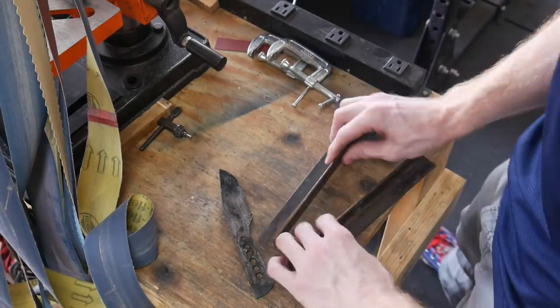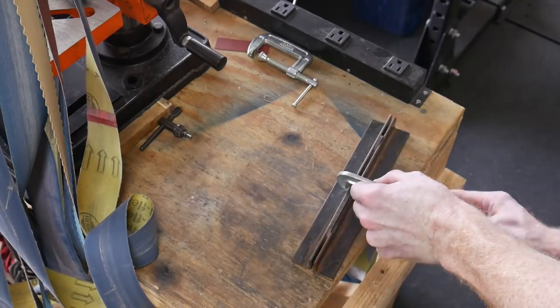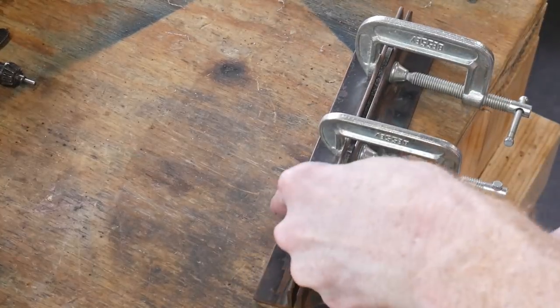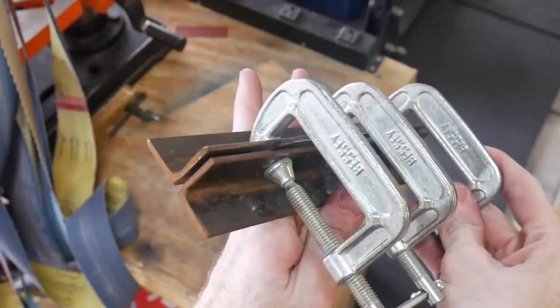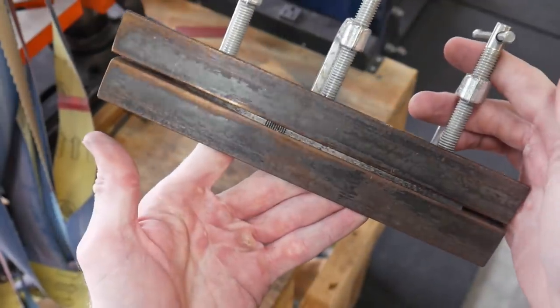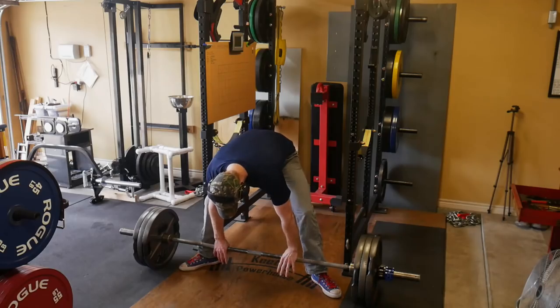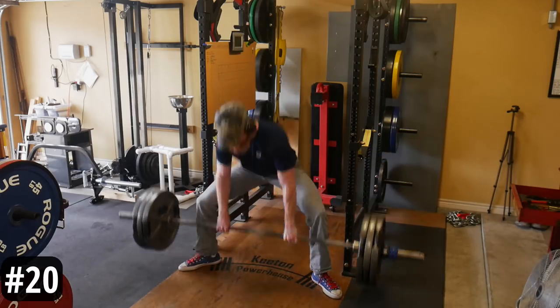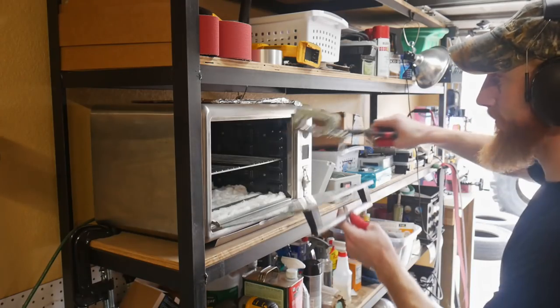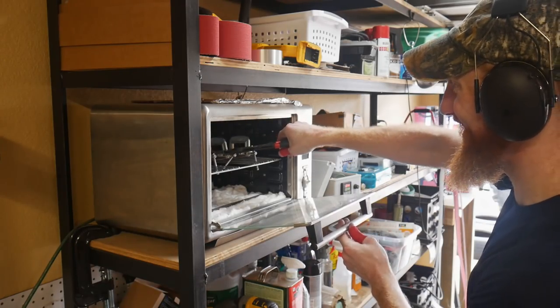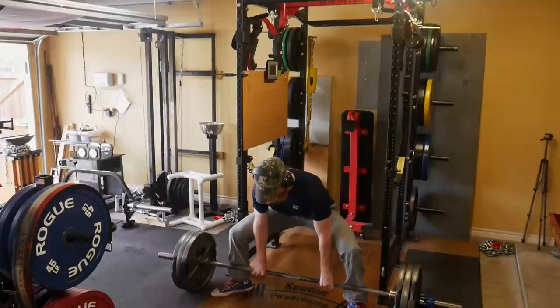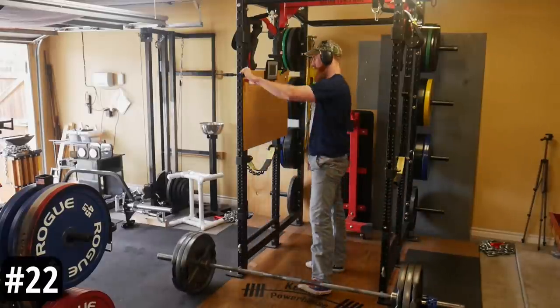We will now be clamping this blade between two pieces of angle iron after we have our holes drilled in the handle scales, and what this will do is hold the blade nice and straight during the tempering process. Last thing I want is for the blade to start warping in one direction or the other, even if it is a slight amount during the heating of the tempering process. We will be tempering at 214 degrees Celsius for an hour and a half cycle, twice.